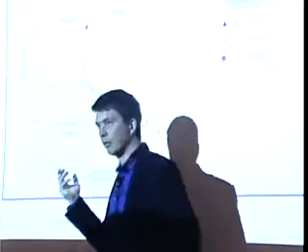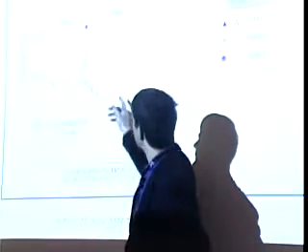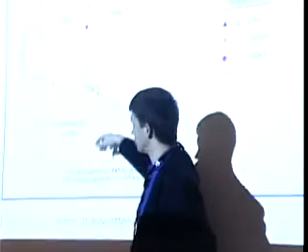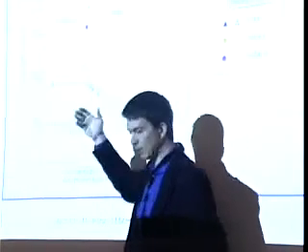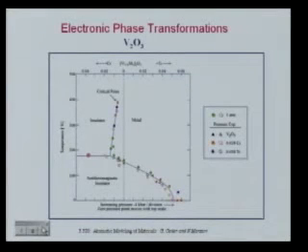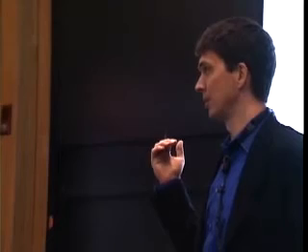And it's completely driven by the fact that in the metal, the entropy of the electrons is higher than in the antiferromagnetic insulator. So this is one of these things that, again, let's go back to our ab initio MD. If it was perfect, but all we did was let the atoms vibrate, we should not get this right. Okay? And it's amazing. Some people get it right, but if you have completely the wrong physics that you allow in your model, there's no reason you should get the phase behavior right.